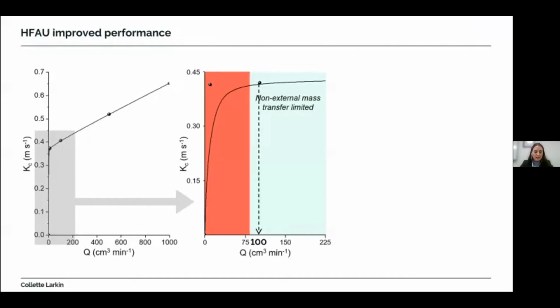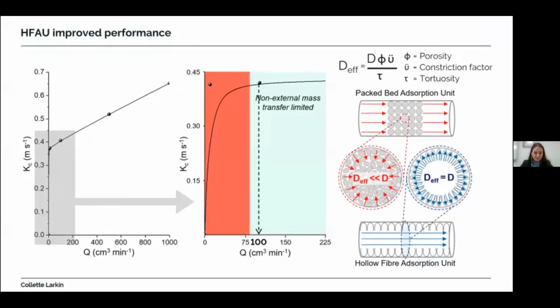Now, if we look at the internal diffusion limitations, the internal diffusion of a gas into a pore can be described by the effective diffusion, D_eff, which is related to the bulk diffusion coefficient D, porosity, tortuosity, and constriction factor of the pore bodies. For the pellets of a packed bed adsorption unit, the internal diffusion of CO2 is limited by a complex network of tortuous interconnecting pathways of pore bodies with varying cross-sectional areas, giving an effective diffusion coefficient that is less than the bulk diffusion coefficient.